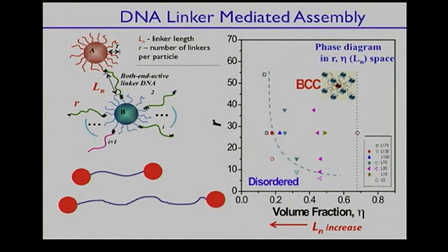When the linkers are relatively short, one particle can feel where another is located, and there is some incentive to go to the crystalline phase. As we go to longer and longer DNA, there is more and more entropy within the chain, so from this perspective, one particle no longer feels where another particle is located. This is something we call entropic elasticity. One way to compensate is to introduce more and more arms connecting different particles, which gives more incentive for the transition from this disordered state, where they don't care about each other, to the state where they do care and the crystal is formed.